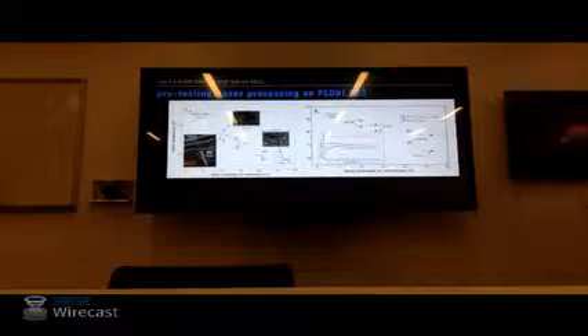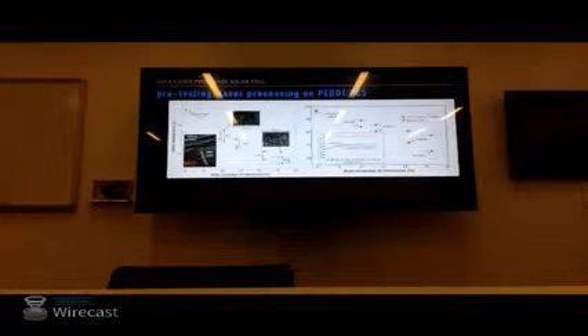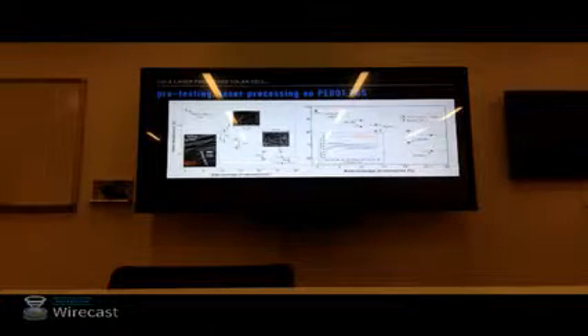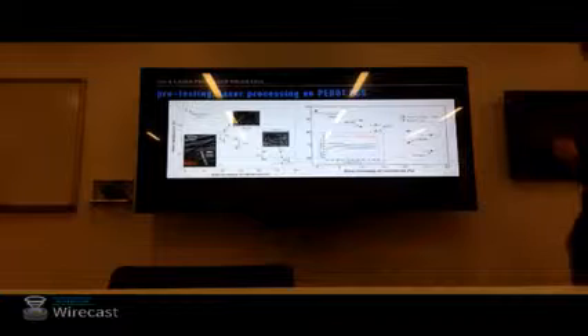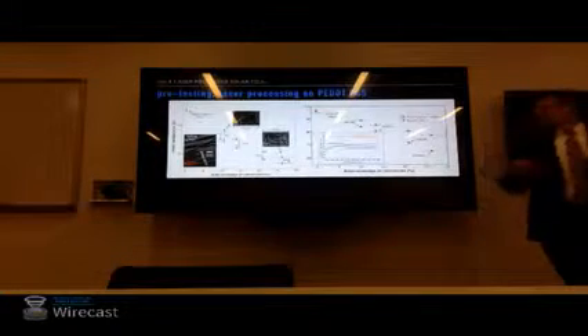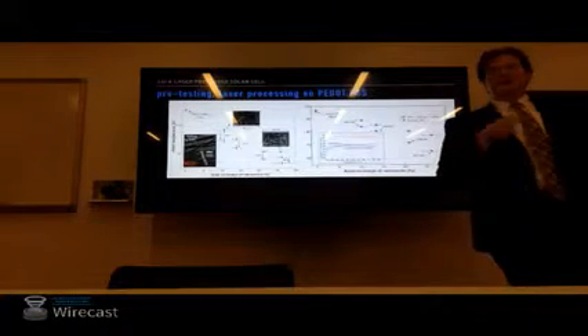We can then look at these devices in terms of their transparency, again reported as area coverage. We can look at transparency in two different ways. Specular, which is what we associate as transparency, how well we can see through a device. And total, which also counts diffuse transmission, so scattering events that scatter forward through our layers are counted in total transmission. What we see is that while the specular tracks very well with the area coverage, the total can be a little bit above. Those scattering events can favor us. And of course, in a solar cell, we don't care how those photons get in, whether it's specular or scattered through. So those green dots are really what we should be looking at.